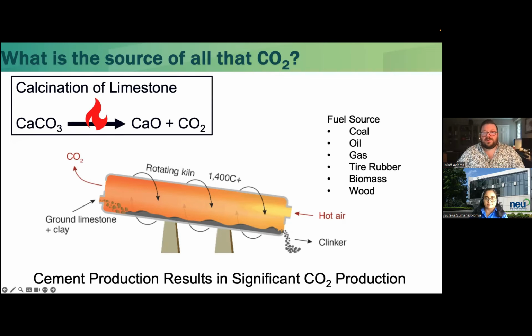But really the main source is from the calcination of the limestone. Limestone is a raw material we put in so that we can get calcium oxide, which is a main component of cement. And when you burn that calcium carbonate, the limestone, when you heat it up, it drives off CO2, so you get the calcium oxide. And right now, in most cases, that CO2 is just being released to the atmosphere. And so that is a huge source of CO2 coming from cement production.